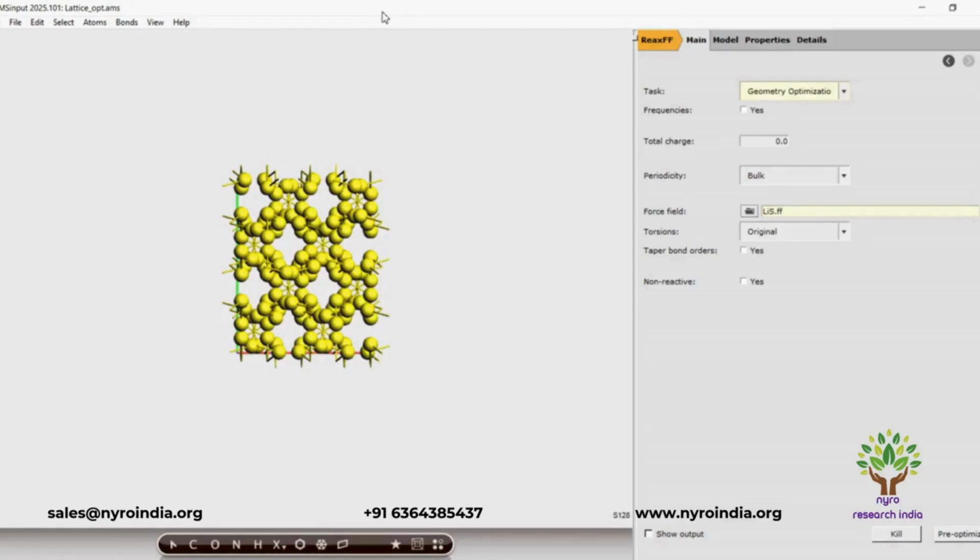The second methodology is ab initio molecular dynamics, which we can perform using DFTB and reactive force field, best for finite temperature diffusion, including lattice dynamics. The method: we need to run the dynamics at the target temperature, track the trajectories, compute the mean square displacement, and then extract the diffusion coefficient using the Einstein relation. We can perform the calculations using either BAND or DFTB and classical MD. Of course, we can use reactive force field or force field engines.